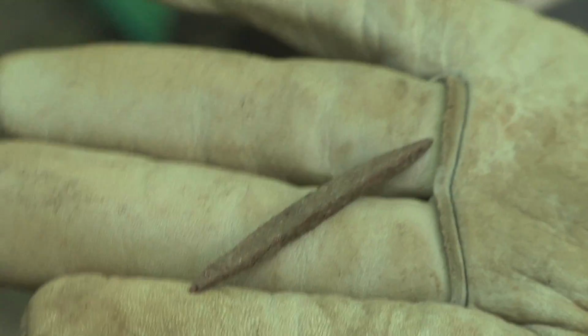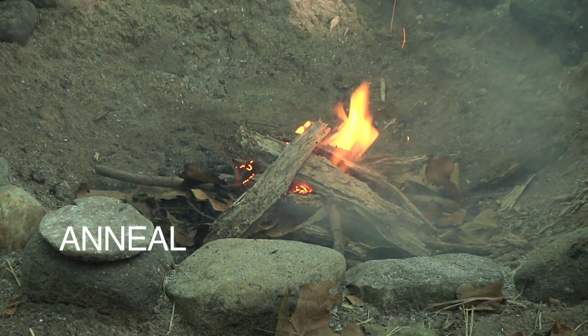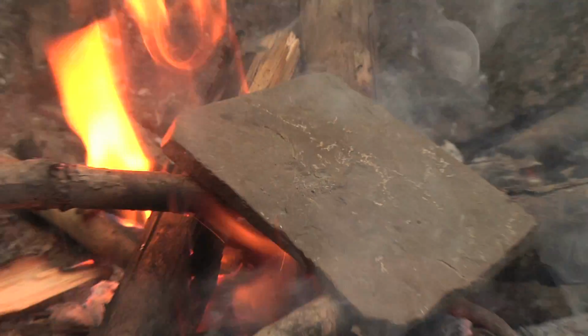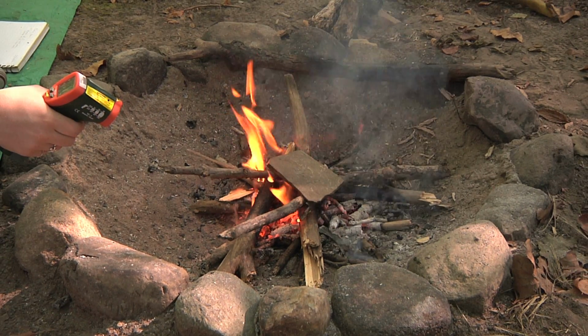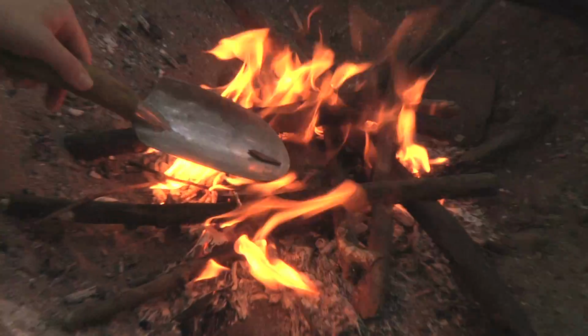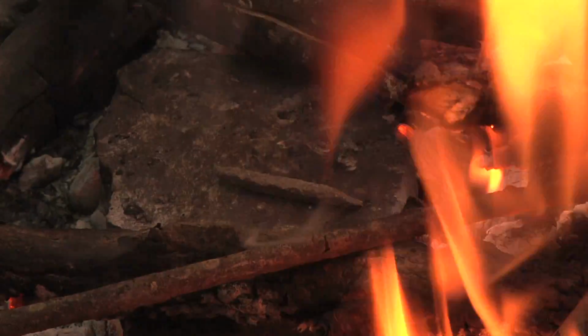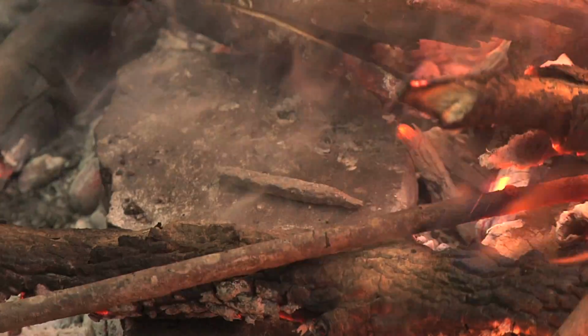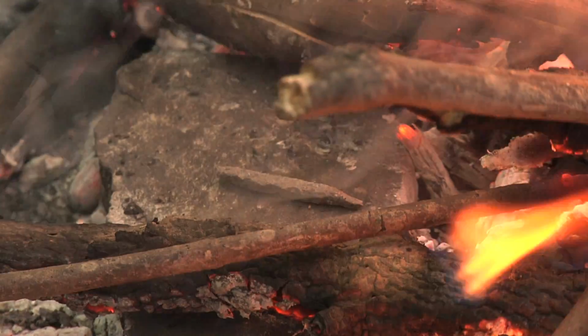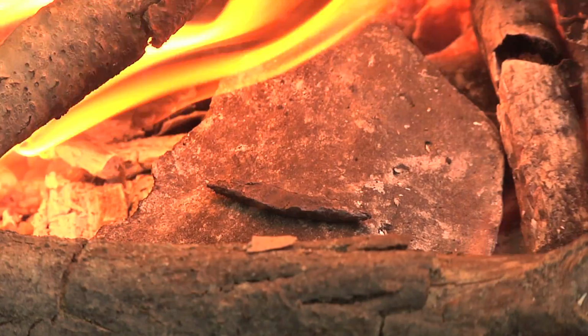We believe that after they cold worked the pieces, the prehistoric people would have heated them up in the fire or annealed them to relieve any internal stresses that may have arisen from the cold working. They would have needed a good temperature in the fire for this annealing, because you don't want it to be too hot so that the piece melts or becomes weaker, but you want it hot enough that there is something that relieves the stresses. An easy way to tell a good annealing temperature is by the color of the piece, actually looking at the piece as it's in the fire.